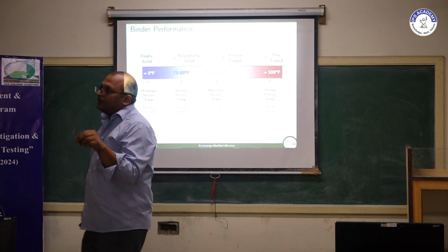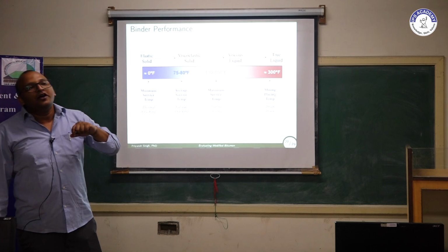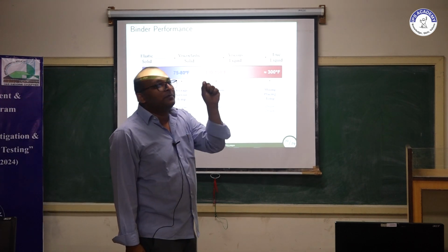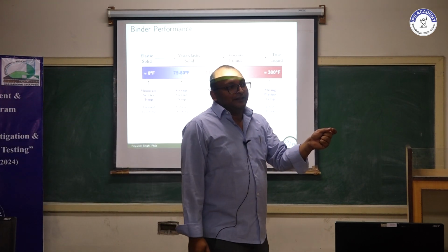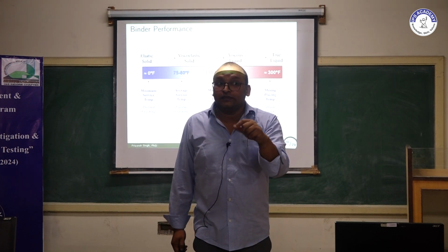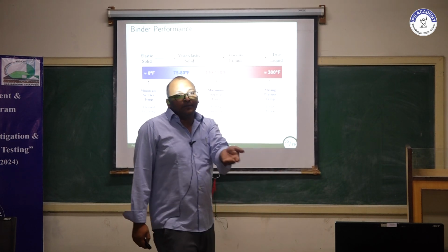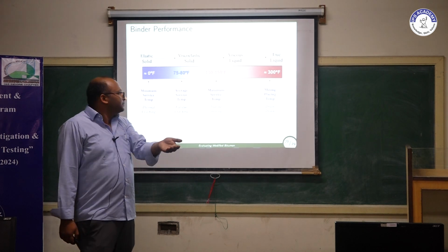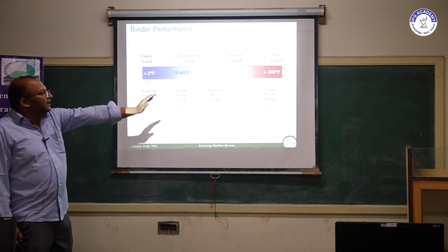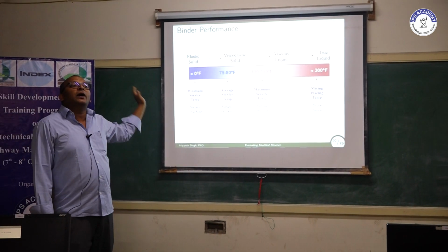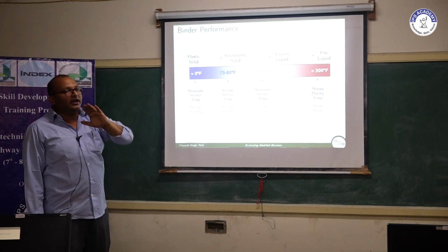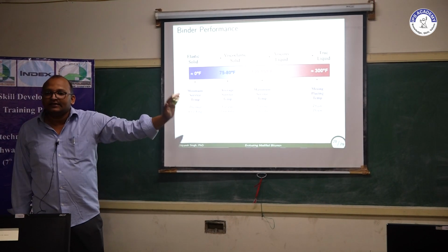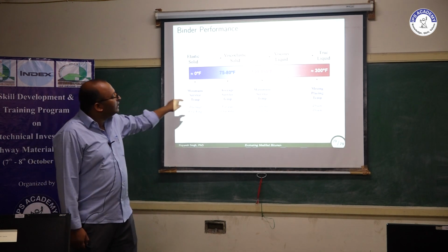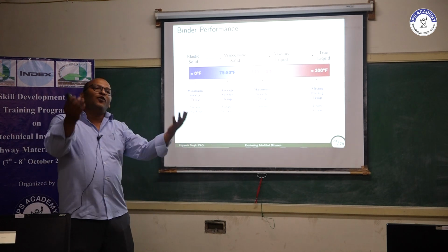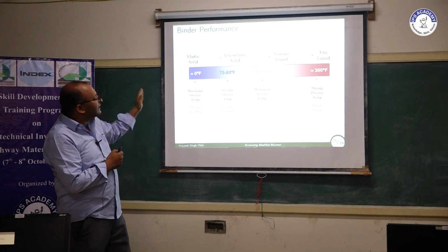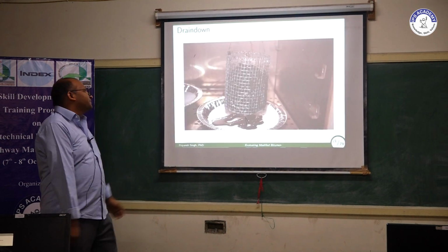Now the next important temperature which your binder will undergo is the temperature at which you will mix it with aggregate. That is going to be 135 degrees Celsius or maybe 160 degrees Celsius, depending upon your mix design. So these all temperatures are very important in order to see the binder's performance, and that is why we have designed a spectrum of tests in order to characterize binder at all these temperatures. Now let's see what different tests are there in order to characterize our binder at these service temperatures.